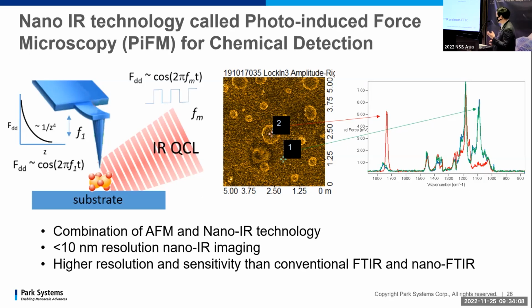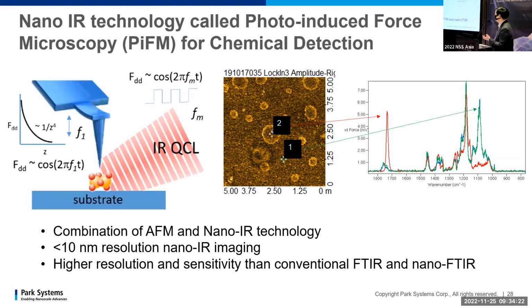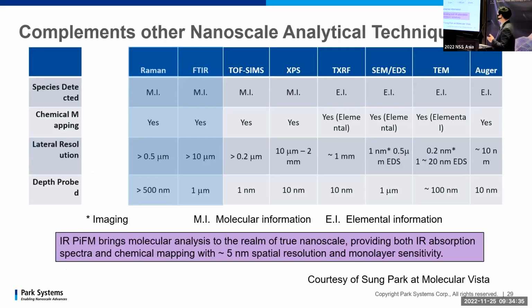And then those molecular vibrations make different attractive forces. The AFM tip is so sensitive, it can detect how the attractive force is changing here. And then we found out this signal is really well aligned with the Fourier transform IR spectroscopy, the FTIR. So when we compare this with the other technology, the transmission electron microscope,